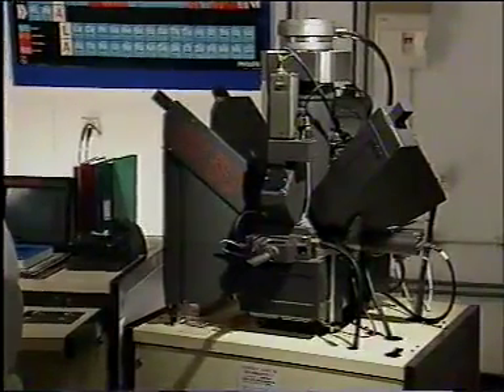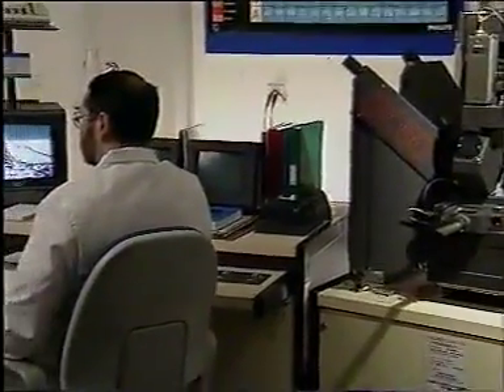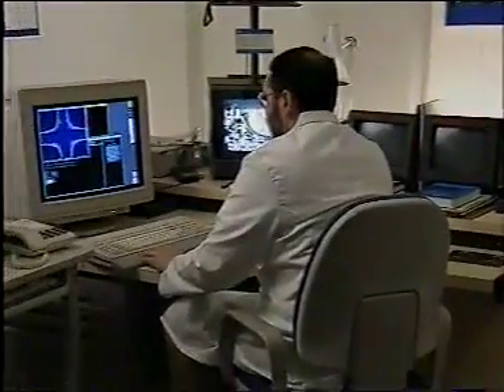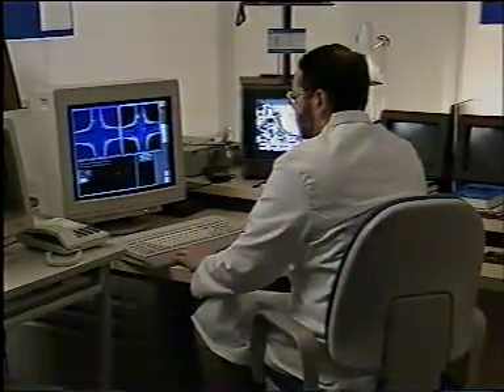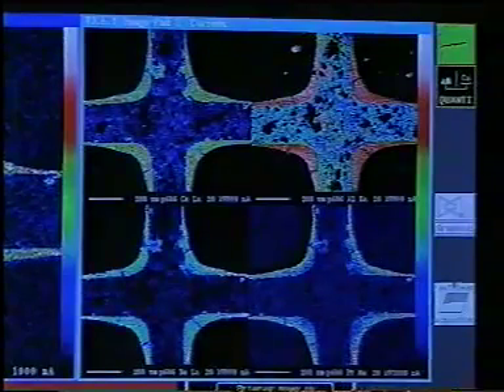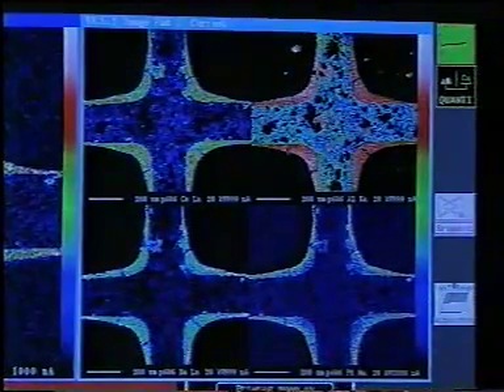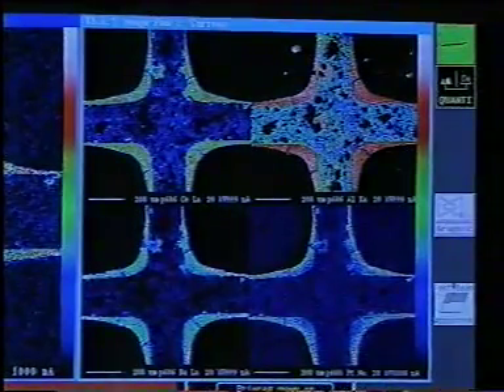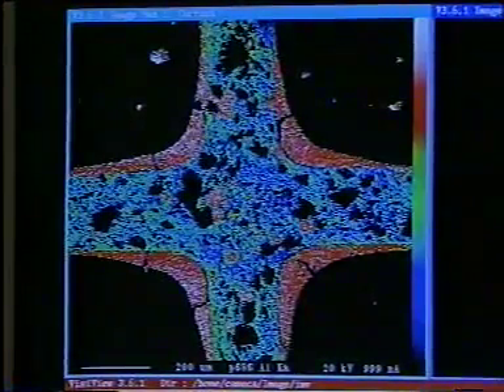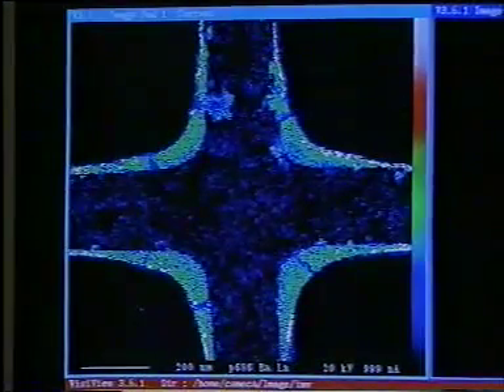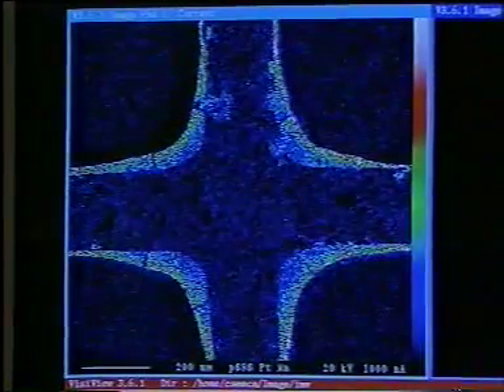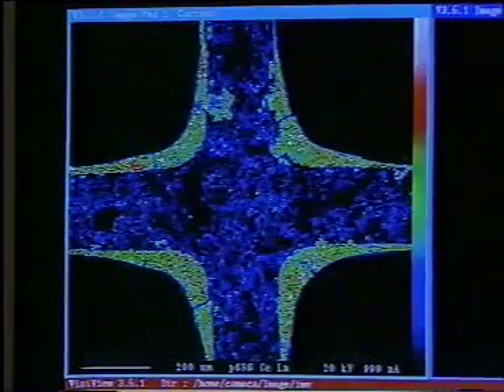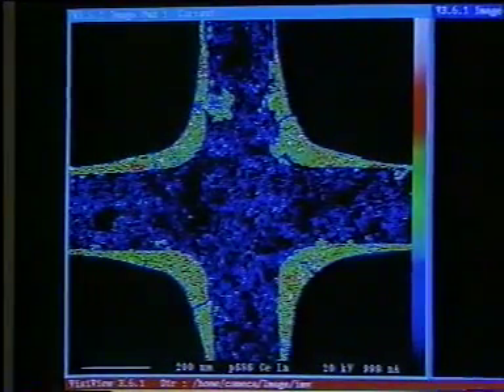An adaptation of the principle of the scanning electron microscope can determine chemical composition by measuring the energies of X-rays emitted from the sample. The technique is known as electron microprobe analysis. The image produced is coloured by the computer to show the distribution of the various elements present in the sample, white being the highest concentration. Here you can see the distribution of the aluminium and the barium of the wash coat. The active catalytic ingredients, platinum, rhodium and cerium, are shown as having much lower concentrations. You can see how the concentration of platinum is much higher at the surface of the wash coat than in its bulk. That's deliberately so to increase the total catalytic action.